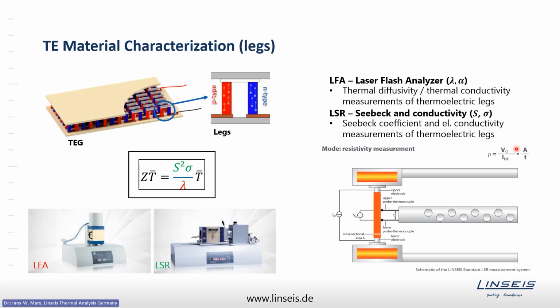In the same machine, in the same setup, but in another measuring mode, you may measure the electric conductivity. Again, the thermoelectric material is placed between these two holders. In this mode, an electrical current is fed through the thermoelectric material. By knowing the intensity of the electrical current and measuring the voltage drop over the material, and knowing the geometry, the surface, and the distance between these two probes, you may calculate the electrical conductivity. So you get Seebeck coefficient and electric conductivity from the LSR machine and the thermal conductivity from the LFA machine, so that you can calculate the figure of merit.